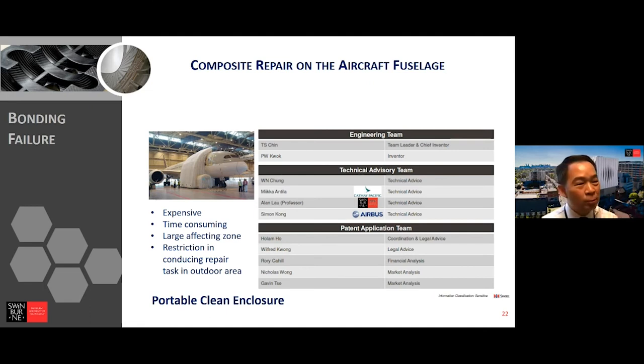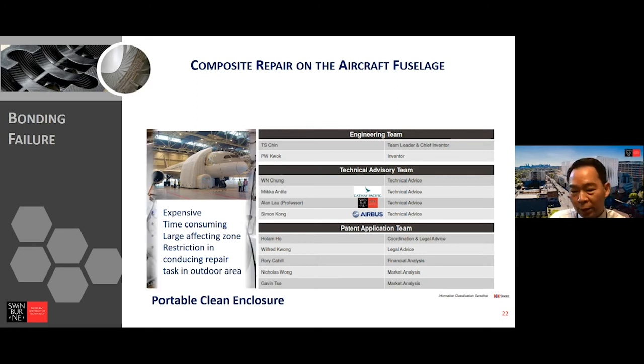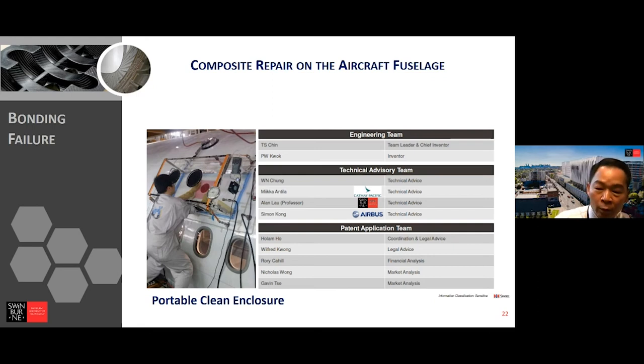This is only for demonstration, but in reality a lot of repair tasks are actually done on the runway, and the runway is not very flat, depending on the country. So what we did is work with HAECO to develop what we call the enclosed chamber. This chamber controls all the environmental conditions, pressure, humidity, and also removes dustiness, with UV resistance, to avoid any damage to the repair during the repair process. So this is also a very good area that we may consider. Of course, this may not be about composite material itself. It's about how to develop a device to assist the composite repair.